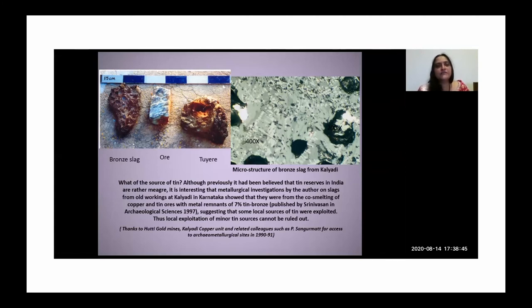So what was quite interesting was that I did find some slags from the Kalyadi region of Karnataka, and you're looking at some of the slags and the tuyeres and so on. And when I looked at the microstructure of the slag, you're seeing the same glassy fayalite structures and so on, which I was pointing out in the earlier copper slags. But the metal here, the prills here were not copper prills, but bronze prills with 7% tin, which is a bit of a surprise.